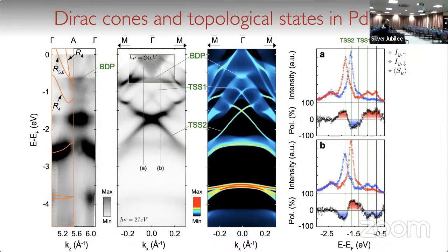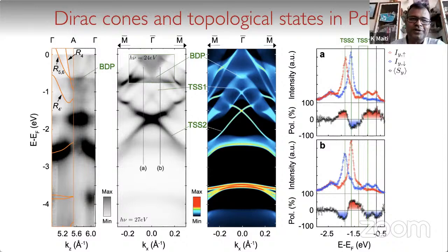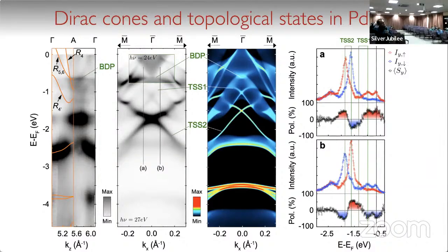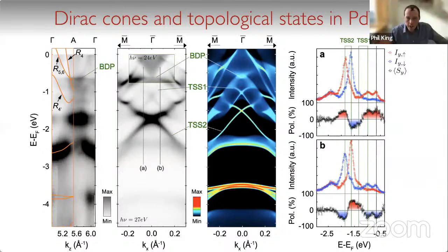Actually something else is in my mind. For example, in the superconductor bismuth palladium, we do see two surface states at the same momentum, one on top of another. That's mostly because of broken inversion symmetry. No, I think that's because you have two different kinds of surface. If you have twinning, then you can get these states for two different surfaces in your spectrum. Okay, so this is not the case here. Yeah, that's not the case here, because this is a Van der Waals material, and so you get a nice clean surface termination. Thanks a lot.